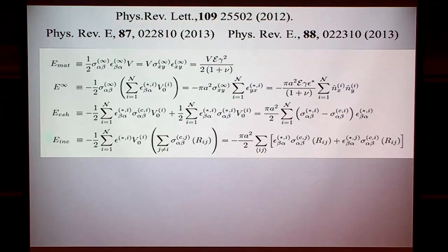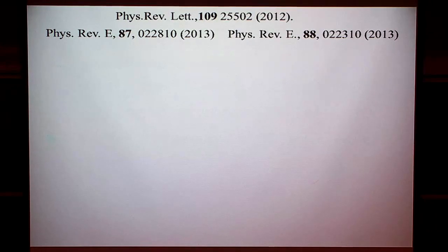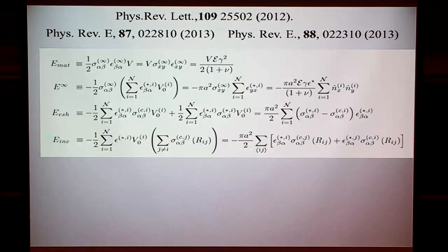So it's difficult to minimize all the energy of all these things. So let's start with very large gamma and ask what will be the prediction if we want to minimize this. And this is depending only on the orientation. You see these Eshelbys, which are quadrupolar, can look like this, or can look like this, or can look like, I don't know, any other sort of thing. And when you minimize this term, you see that the minimum is occurring when all of them are equally phased.